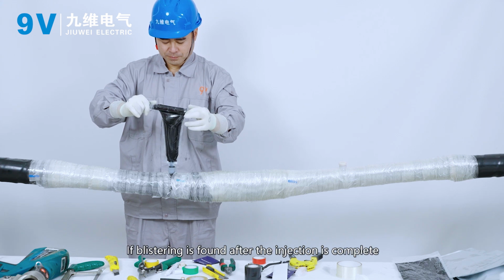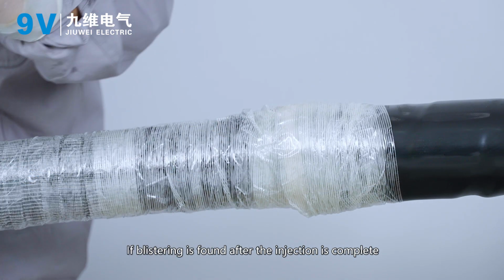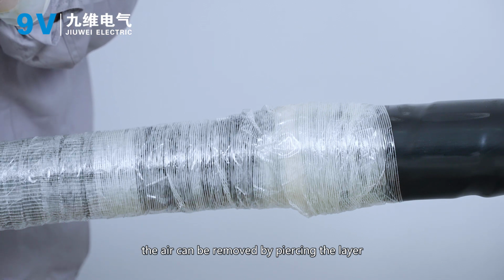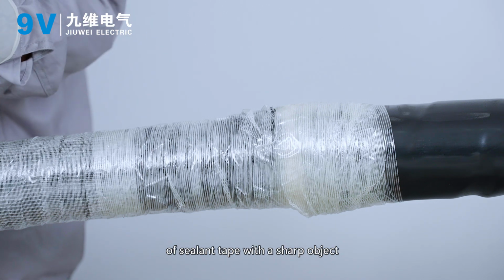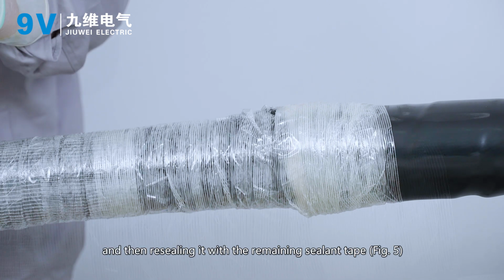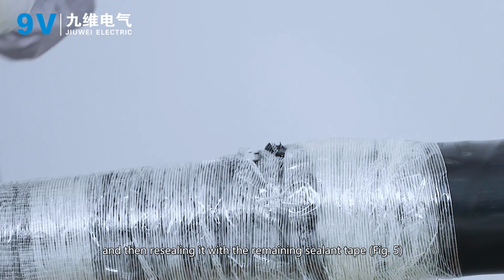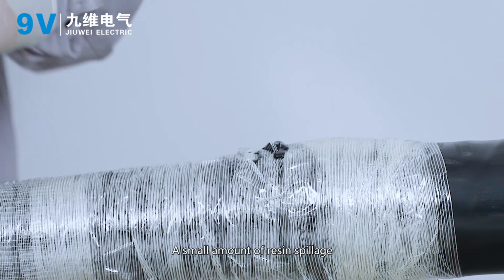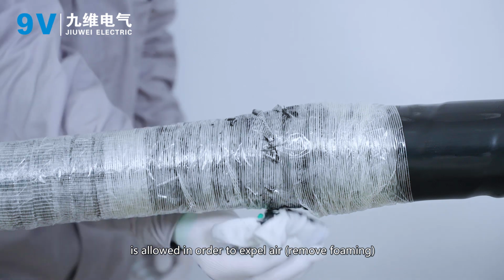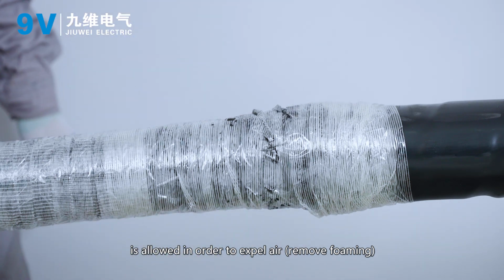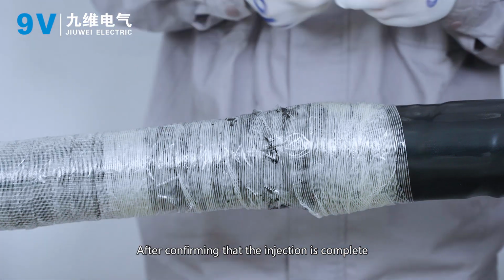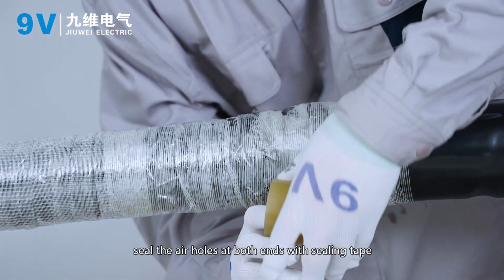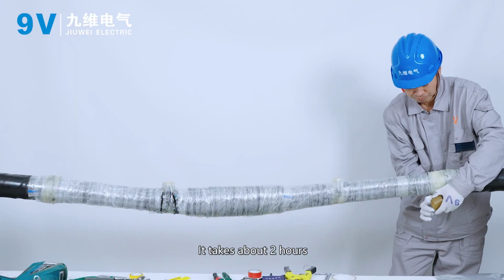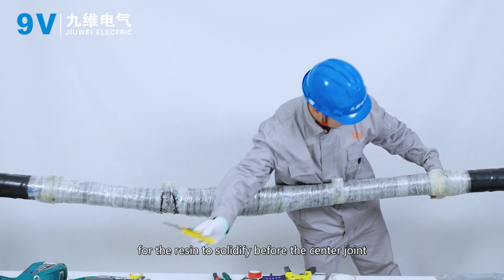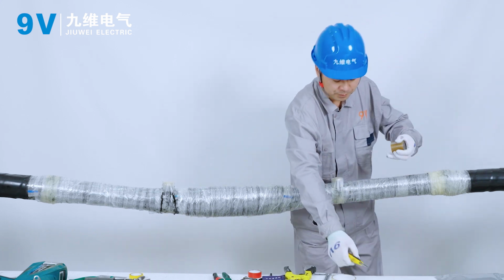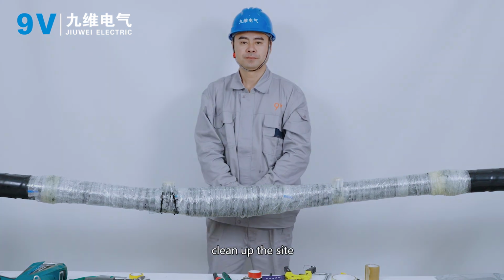Figure 5. If blistering is found after the injection is complete, the air can be removed by piercing the layer of sealant tape with a sharp object and then resealing it with the remaining sealant tape. Figure 5. A small amount of resin spillage is allowed in order to expel air. Remove foaming. After confirming that the injection is complete, seal the air hose at both ends with sealing tape. It takes about 2 hours for the resin to solidify before the center joint can be moved. Installation finished. Clean up the site. Thanks for watching.